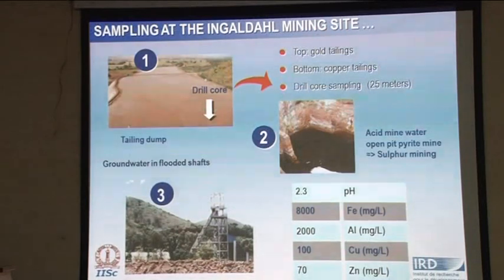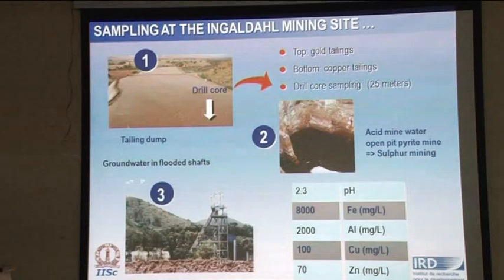And then you can see that immediately after any rain event, there is acidity generated and the proliferation of the microorganisms. So we have isolated the microorganisms from here. This, what you see here, is the adit that is done for the extraction of copper, and you can see that at lower levels, once you go to great depths, the groundwater can get contaminated because of the acidity generated.